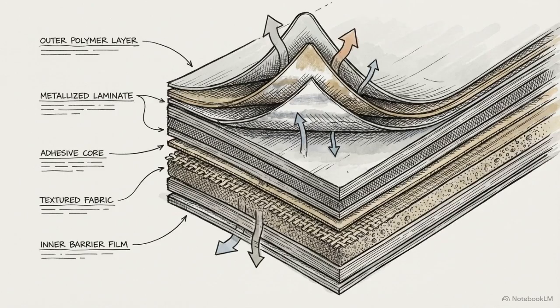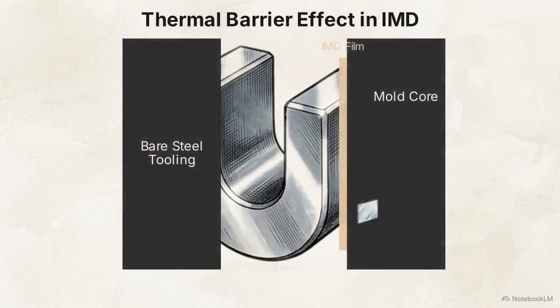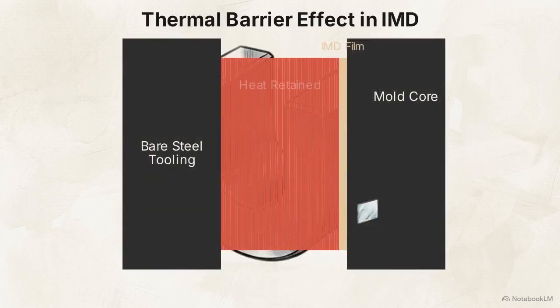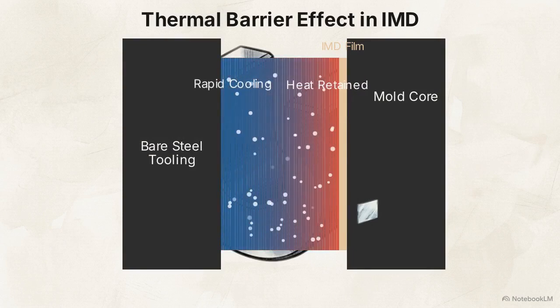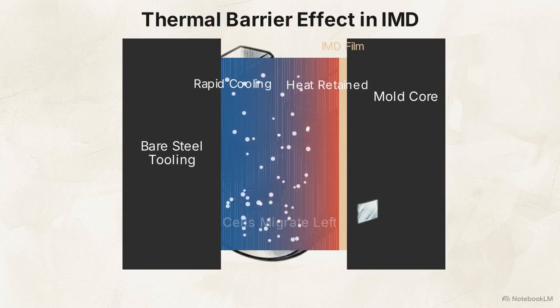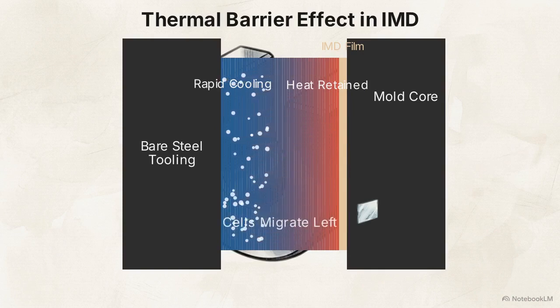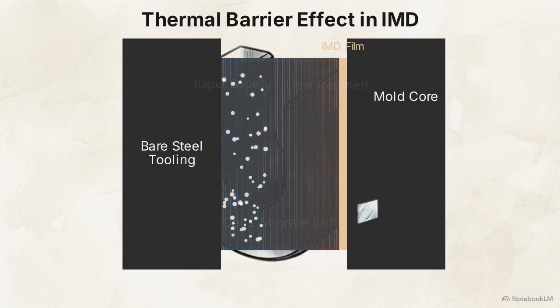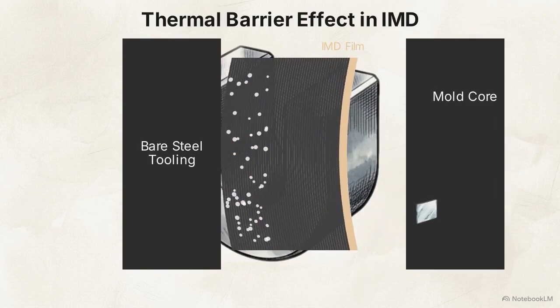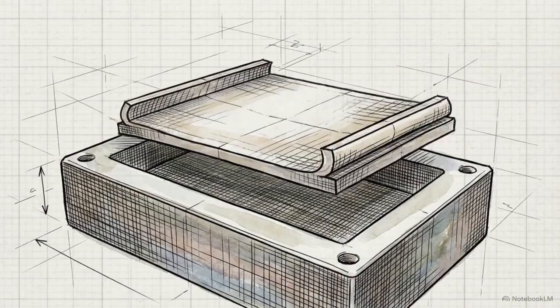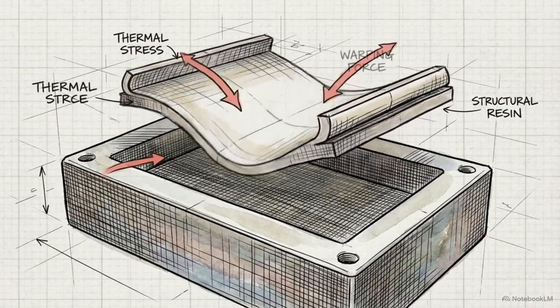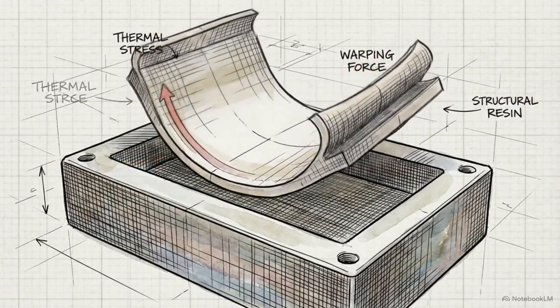This utilizes significantly thicker polycarbonate sheets or metallized laminates. These thicker films introduce a severe thermodynamic complication. They act as intense, localized thermal barriers inside the mold. With IMD, the film side retains heat, while the steel cools rapidly. In microcellular foaming, this imbalance creates chaos. Gas cells migrate away from the hot film toward the cooler steel, shifting the core off-center and structurally imbalancing the cross-section. The result of this uncompensated thermal asymmetry is a part severely twisting and warping the moment it ejects from the press.